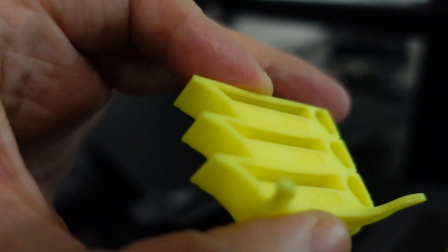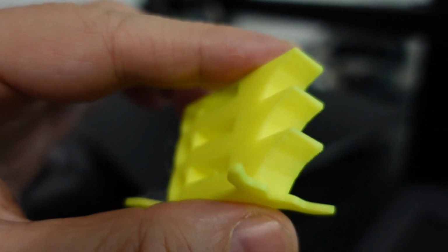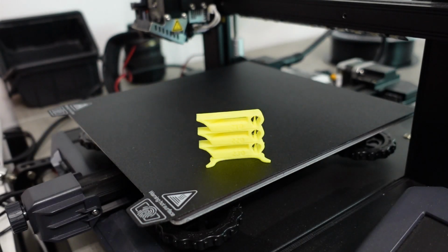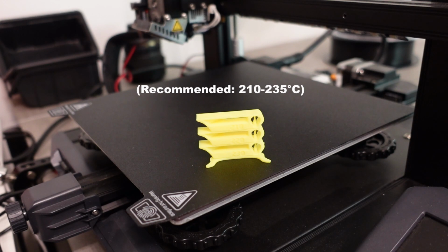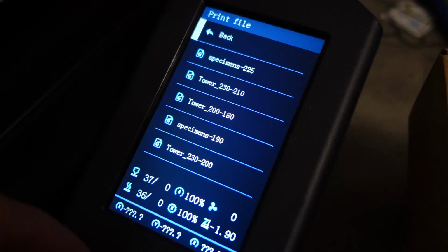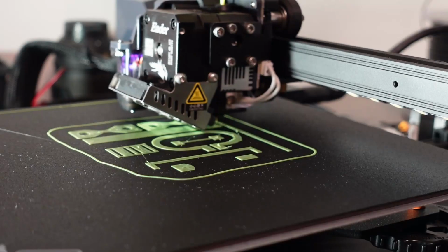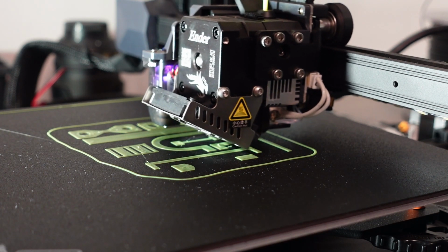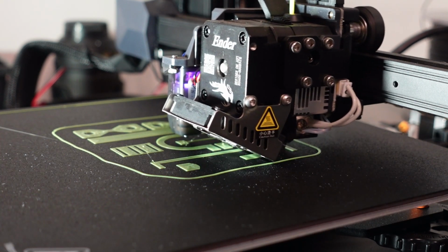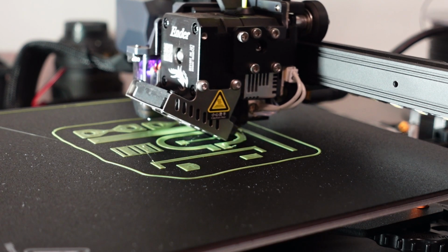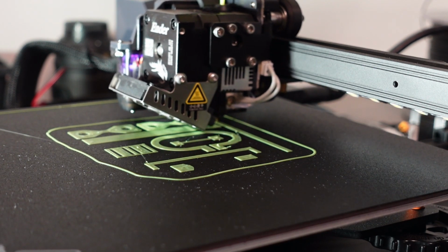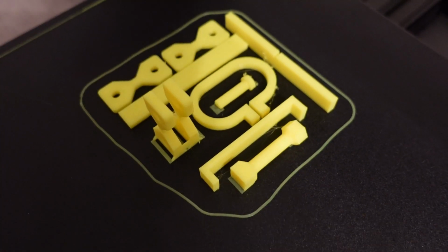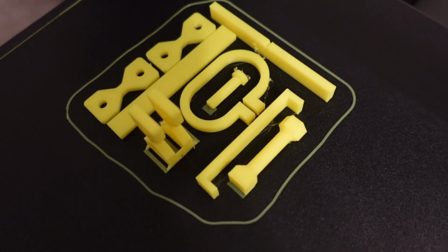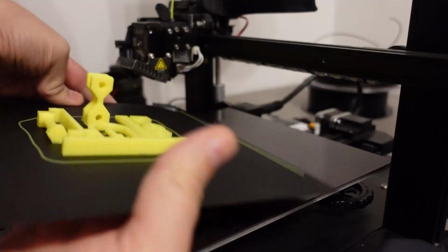And I don't have to mark this one because this is the only one which is not in black color. And I print all test objects on 225 degrees Celsius, which is approximately in the middle of the recommended printing temperature range. Well, this is another perfect first layer. I can see a few strings here and there, but I'm not worried about it. And this will also be printed during the night without supervision. Overnight printing successful, and I can see just a few strings, otherwise it is great printing.